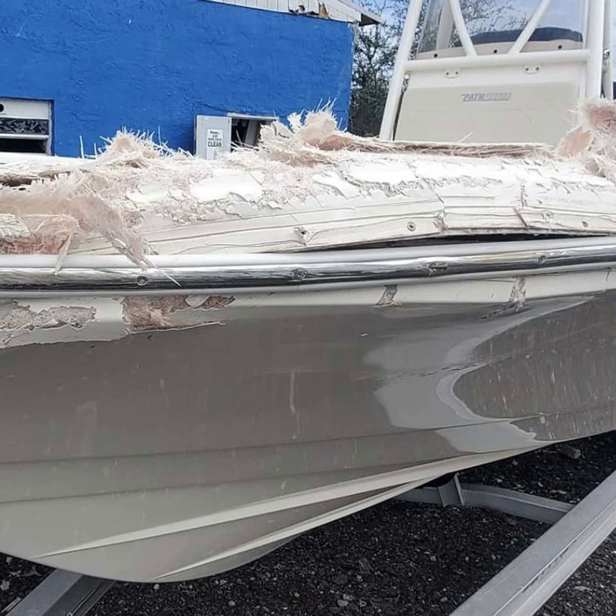Yeah. And if you can reach in from the back, I recommend that you put your patch on the back before you lose the shape by grinding the front. Then you can grind the front back to meet the patch on the back and glass in between from there. So that's a way that you would address a puncture or a fracture or something like that.